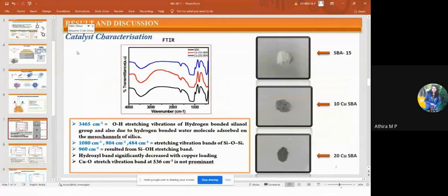Next, moving to the catalyst characterization section. This is the FTIR spectrum of SBA, 10 copper SBA, and 20 copper SBA. The presence of a broad band in the low frequency region, 3000 to 4000 cm⁻¹, centered at 3465, was characteristic of the OH stretching vibration of hydrogen-bonded silanol groups and hydrogen-bonded water molecules on the channels of silica.